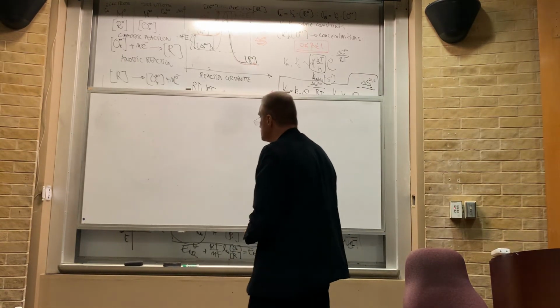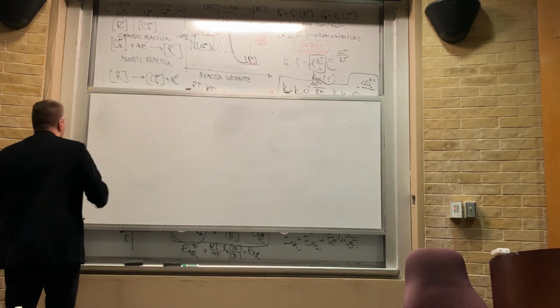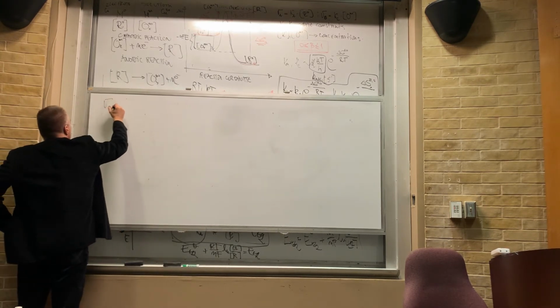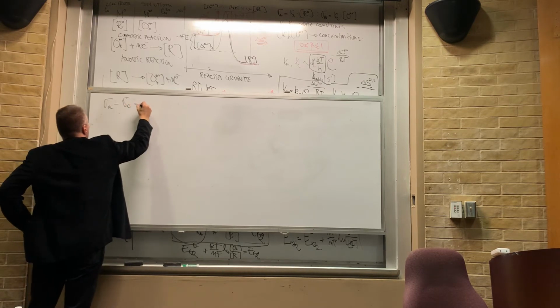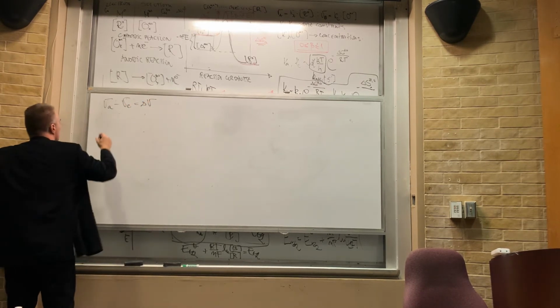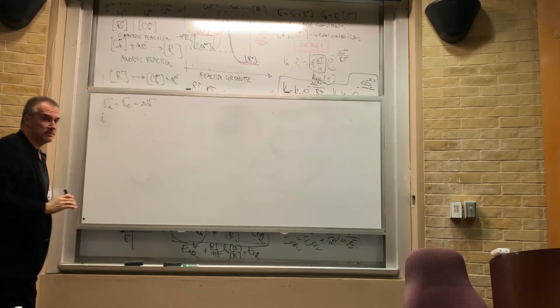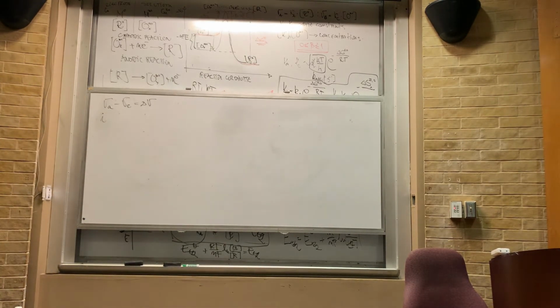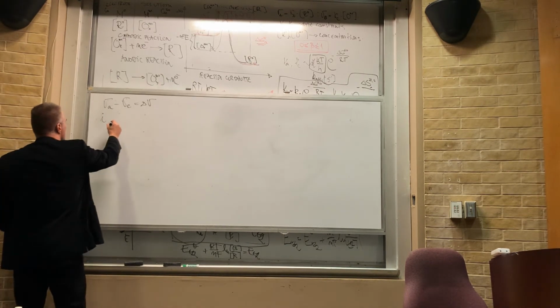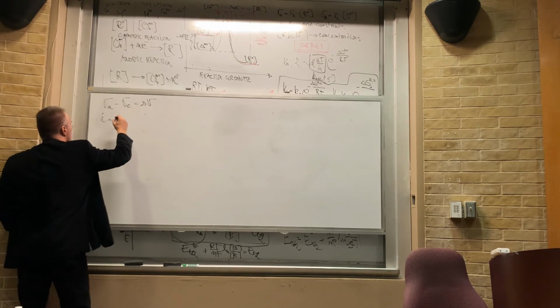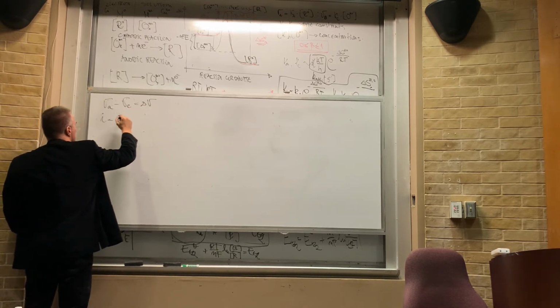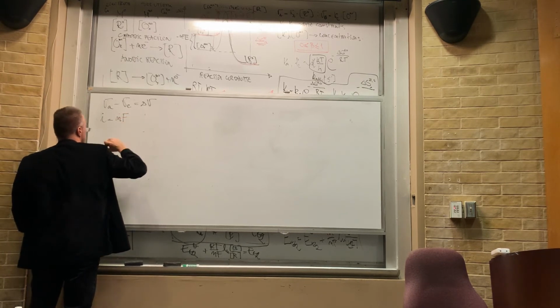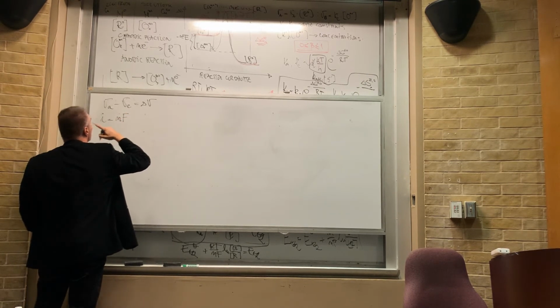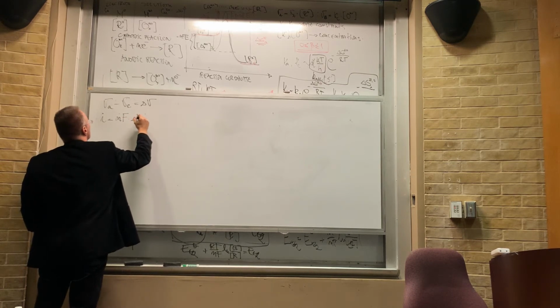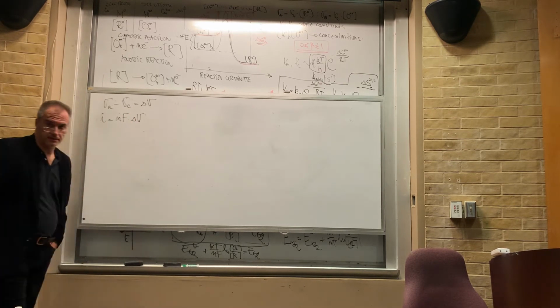So what I'm going to say is that I'm going to have the rate of anodic minus the rate of cathodic reaction being equal to delta R. But at the same time, I'm going to have a current that is the manifestation of the different rates, because current zero means the rates are equal. If this is some kind of moles per second, then if I multiply this by the number of electrons transferred across the interface times the Faraday's constant, which corresponds to the charge of a mole, and then delta R, I'm going to get the current, right?